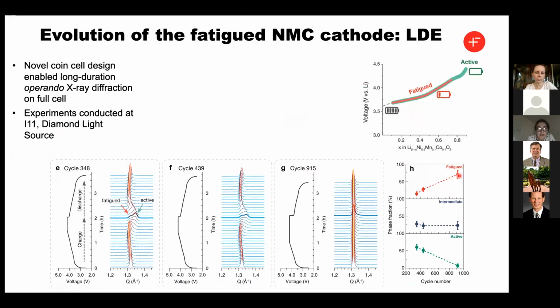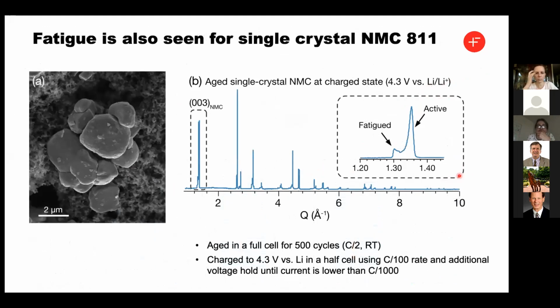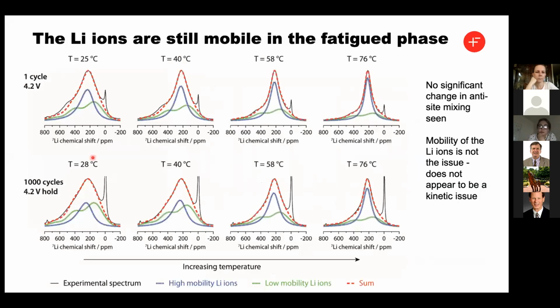And what we think is going on there is quite interesting. So we've looked at single crystals. I talked about these single crystals as being the next stage, and you get exactly the same problem in these materials. So it's not a problem associated with particle cracking and fracturing. It's to do with something else. It's not a problem with lithium mobility. We do the same lithium mobility experiments, and the lithium ions are still mobile in these materials.